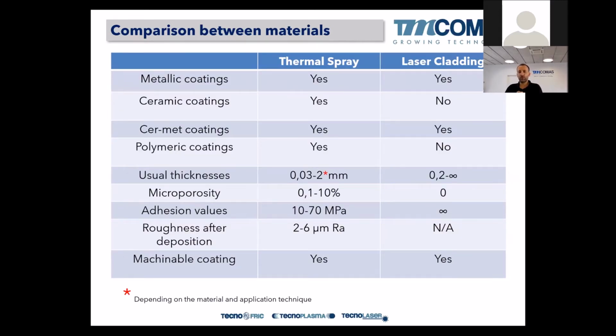The final comparison slide is more about the properties of the coatings. In thermal spray, we can spray metallic coatings, yes. In laser cladding also. Ceramic coatings in thermal spray, yes. In laser cladding, no. Cermet coatings, more or less, mostly tungsten carbide and chromium carbide. In thermal spray, yes, by HVOF, for example. While in laser cladding, yes, but with a higher matrix content, to allow the welding of the cermet. Cermet stands for ceramic metal alloys.